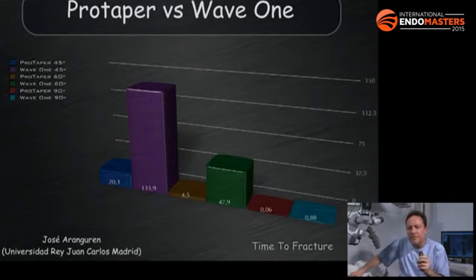It means that even if you have rotation or reciprocation, clinically, whenever you have an apical hook that gets closer to between 60 and 90 degrees, you should never use mechanical files. Neither rotation nor reciprocation. No mechanical files. You shape by hand, and usually what I do is I take any nickel titanium file and I reciprocate or rotate by hand, because you control the pressure, you control the number of movements you do, and you are safer from this side.